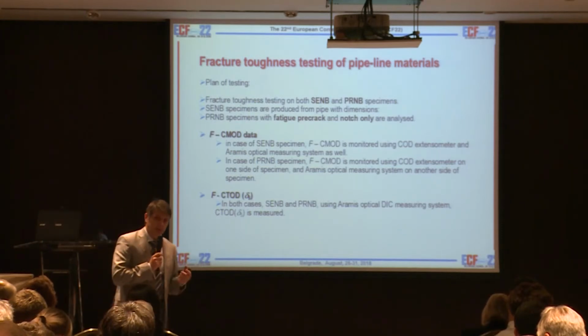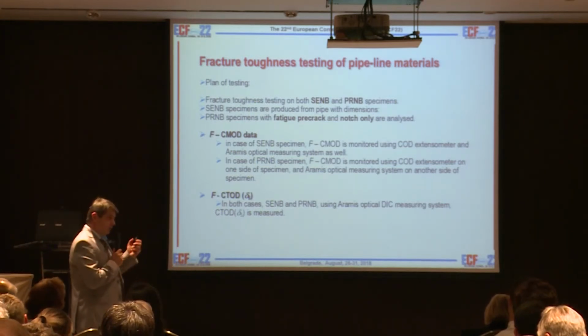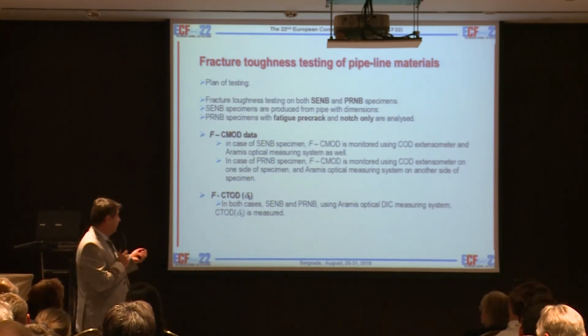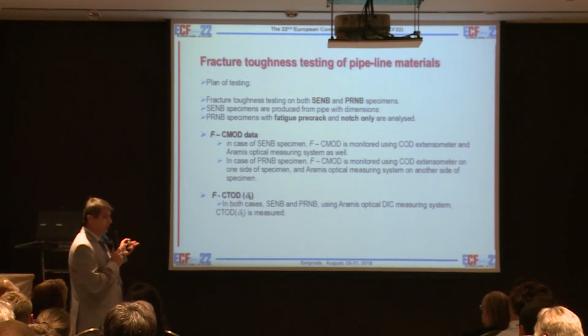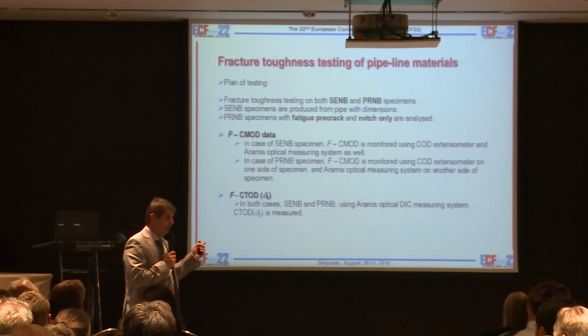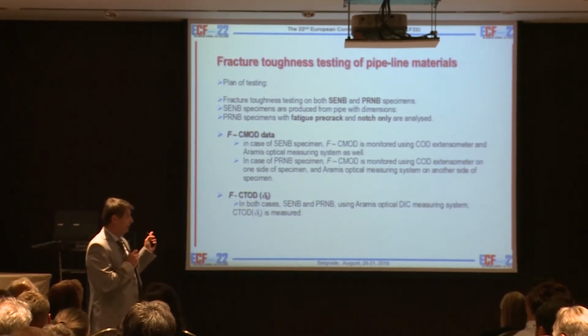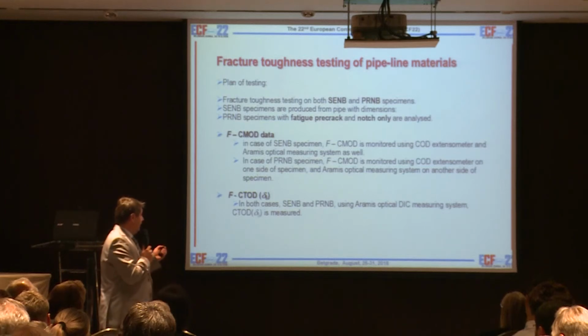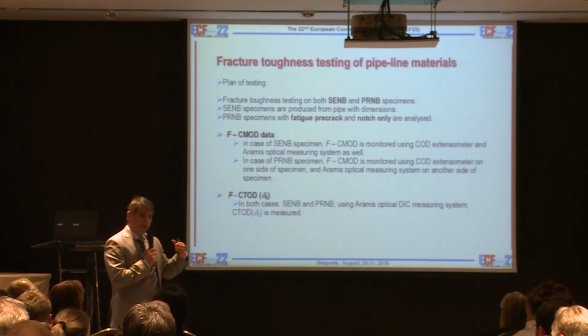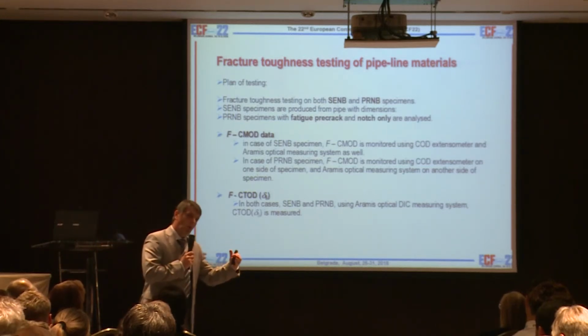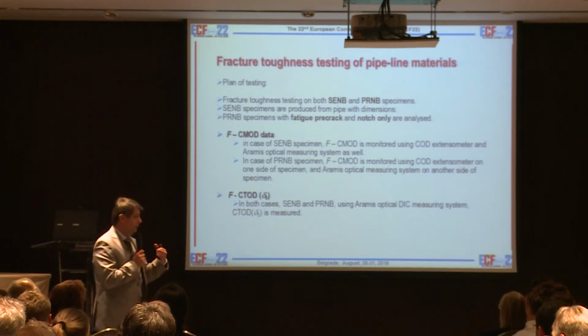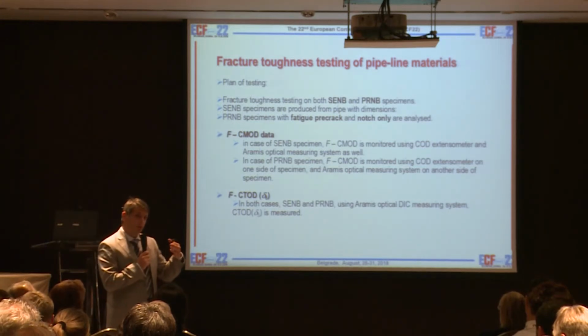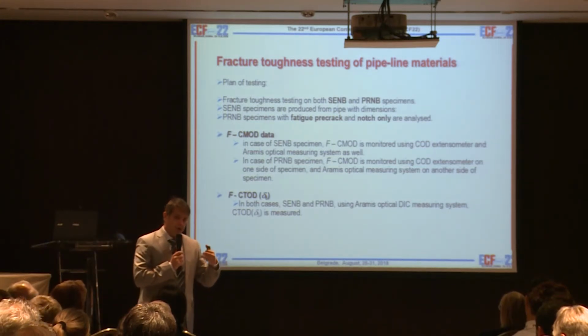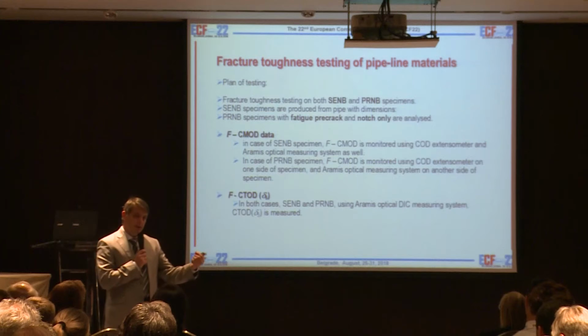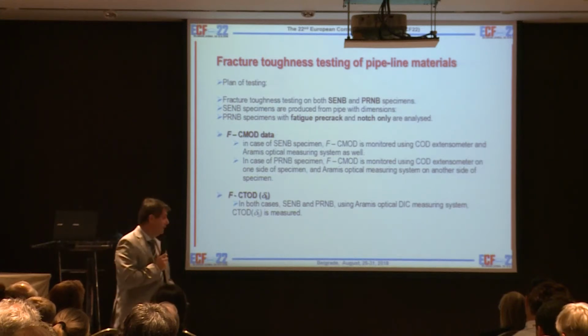so that we avoid too large a plastic zone. Similarly with the pipe ring specimen, we collect data like force and crack mouth opening displacement. Because we have 2 sides on the pipe ring specimen, on one side we put the Aramis equipment for digital image correlation, and on the other side we put just a CTOD clip gauge.